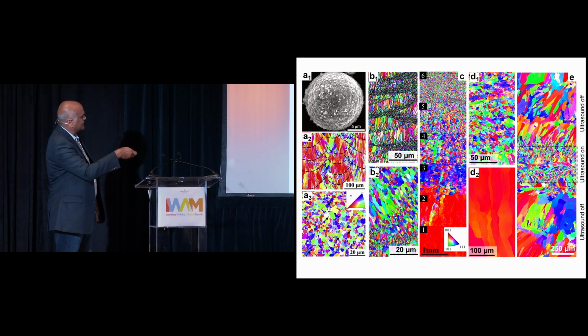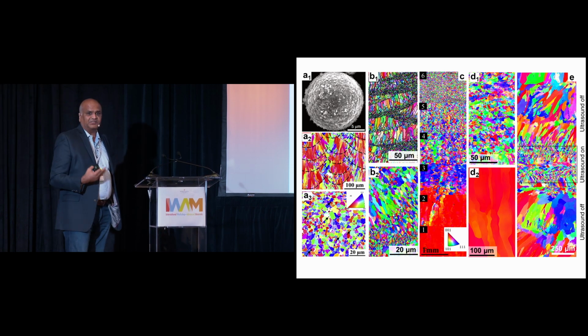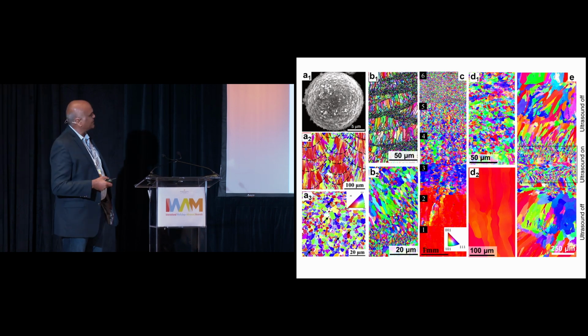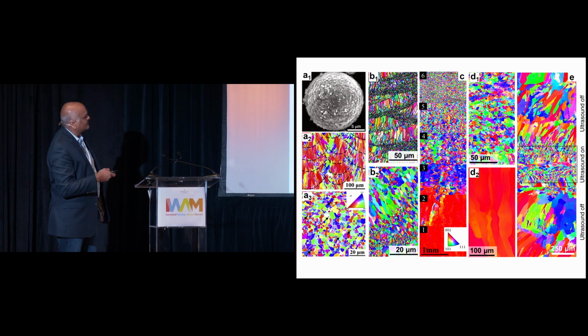This is where we take iron and add aluminum to it. Our idea was that aluminum is lighter, so we want lighter steels. If you take pure iron, this shows all 001 orientation—all red, meaning highly textured grains. As you add more and more aluminum, you are essentially forcing a columnar to equiaxed transition and finer grain size. So these are the things that are possible.